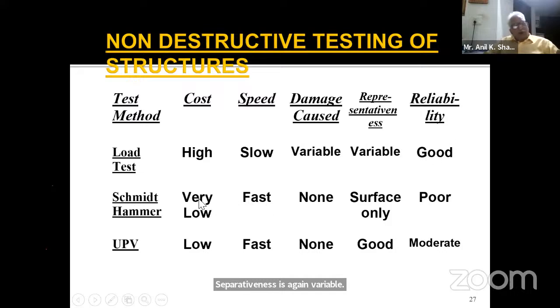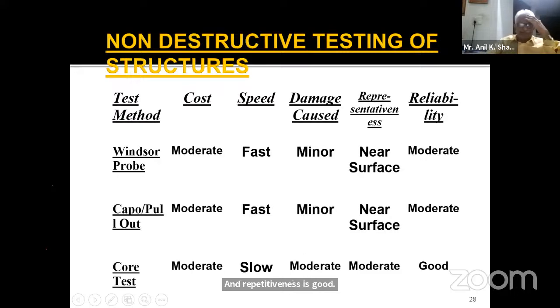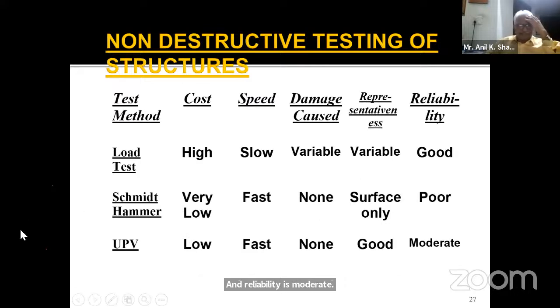Schmidt hammer test: cost is very low, it is fast, and no damage is caused to the structure. It represents only the surface hardness, and reliability is poor. The ultrasonic pulse velocity test gives you the uniformity and denseness of the concrete. UPV test cost is low, speed is fast, damage caused is none, representativeness is good, and reliability is moderate. These are all qualitative tests.